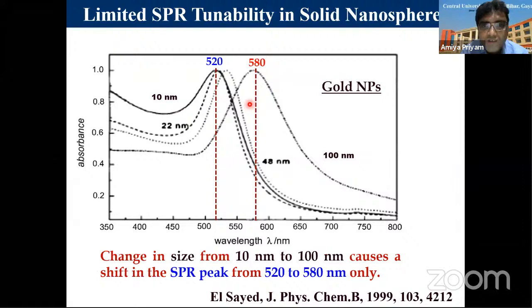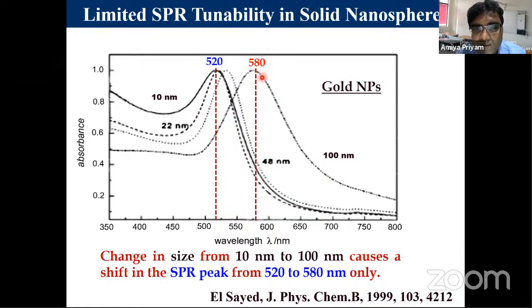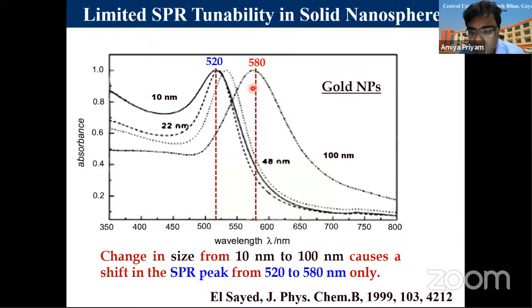But if you talk about it, normally when we synthesize nanoparticles, spherical-shaped nanoparticles of gold or silver are synthesized, and it is found that there is a limitation to the optical properties that they can have. What is shown over here is that whether you make 10 nanometer gold nanoparticles and then slowly go on increasing the size, the maximum change can be to 580 nanometers. Okay, so by increasing the size 10 times, only a 60 nanometer change in the absorption is observed. And this is not useful for applications.